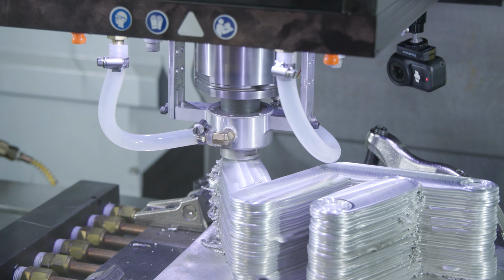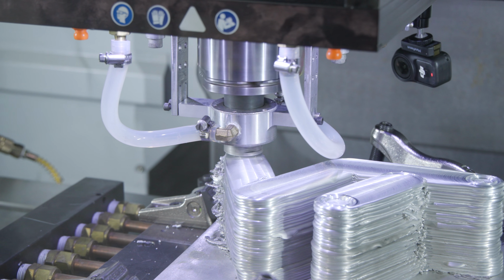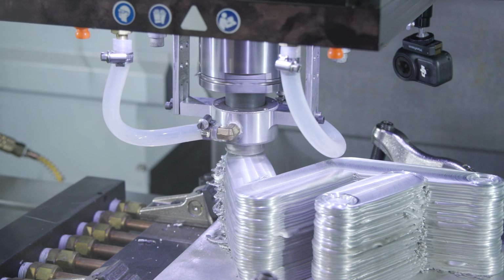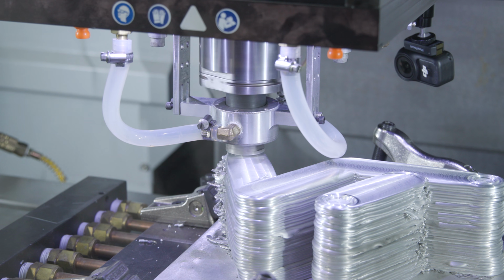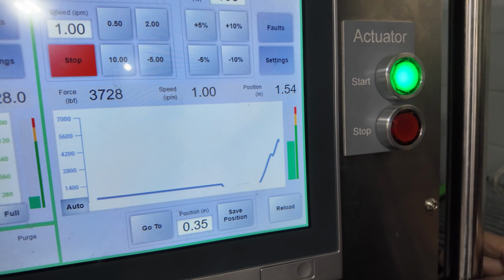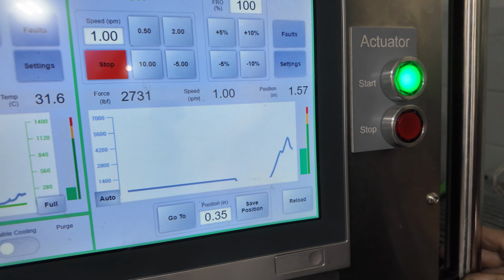We've reached enough load to compressively deform that material and it starts to effectively fail. But once you have enough temperature, then it can flow continuously. So rather than breaking off small little pieces, it's moving almost like a liquid. But it's solid the whole time. And that's yield right there.